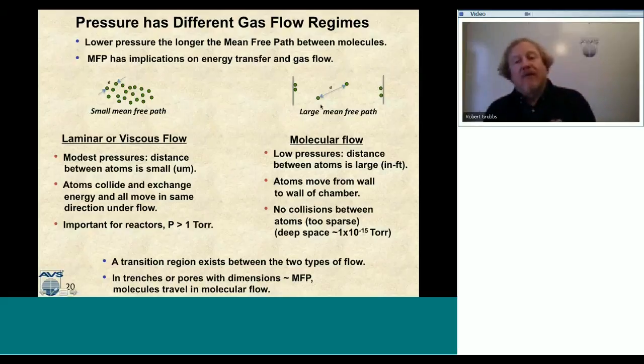Now, molecular flow is over here, when the mean free path is very, very long. And this mean free path can be on the order of inches or even feet. And so what happens in molecular flow is that molecules, as I've written here, go through this adsorption, desorption process and never really run into any other of their beloved molecules in the gas phase. So here in the cartoon, we have atoms on a surface, and then they desorb, and they don't run into anything. They just go all the way to the other side of the chamber wall and then resorb. And then they desorb from there and then reabsorb on the other walls of the chamber. So you have this adsorption, desorption going on when the mean free path is larger than the chamber walls that contain the gas.